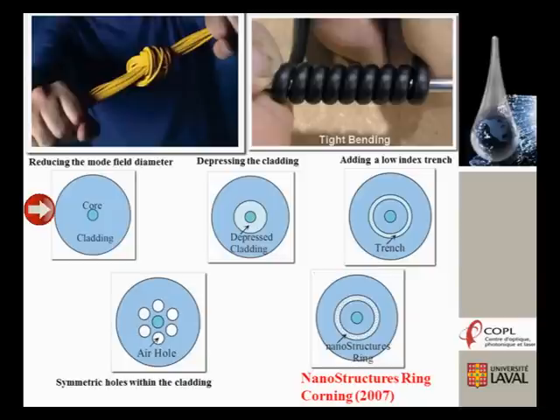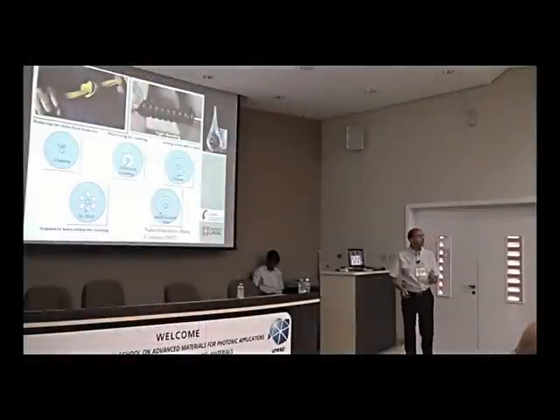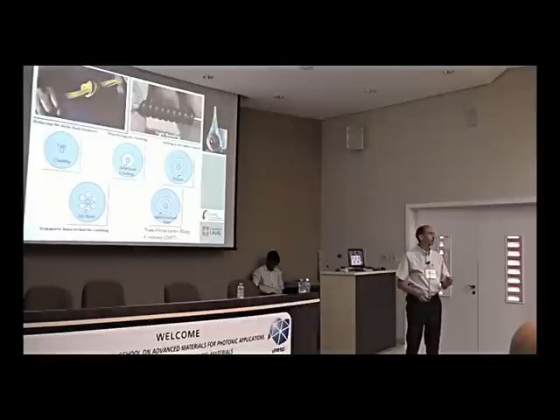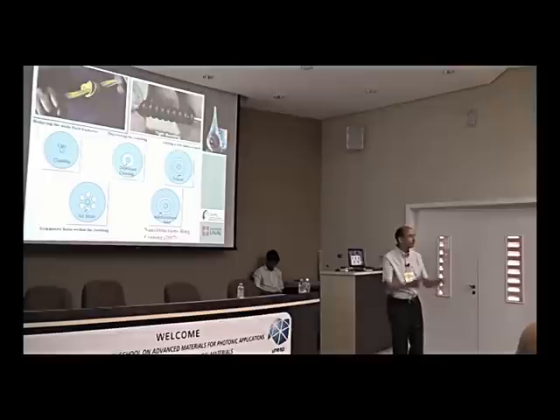The challenge of that is several ones. The first one, if you look carefully in the literature, there are different techniques that allow us to get a higher mechanical property, and one of them, we can reduce the mode field diameter in the way to enhance the mechanical property of the fiber, but this is not enough. And again, from the experimental point of view, it's very hard to get lower than sometimes 5 microns. Using the MCVD technique that we are coming to, I will explain, it's almost impossible. And using this technique is a big challenge.